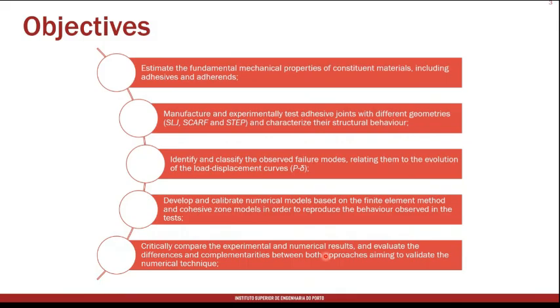So the main objective of this work is to evaluate the 4-point bending behavior of adhesively bonded 3D printed structures. With that purpose, we are going to test 3 geometries: single lap joint, scarf joint, and single step joint, with 3 adherents and also with 2 adhesives, which is one epoxy adhesive and another polyurethane adhesive. In parallel, we want to calibrate the numerical models by cohesive zone modeling so that we can apply this methodology and this framework in the design of adhesively bonded 3D structures.